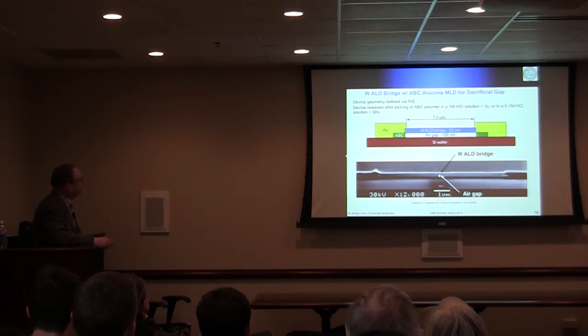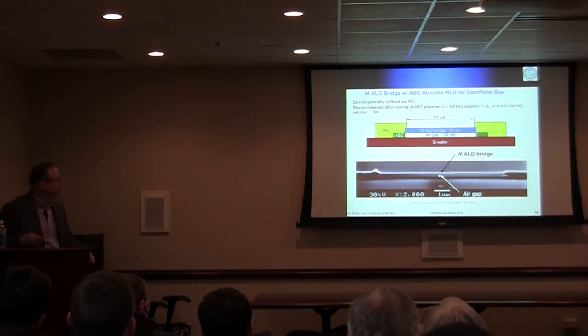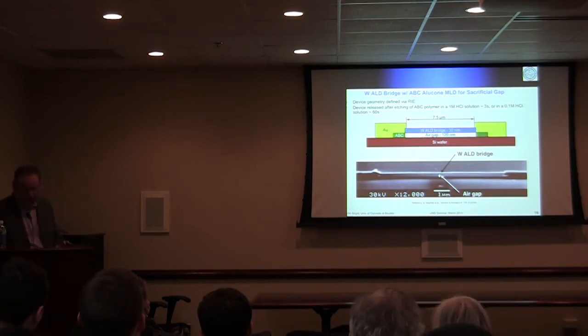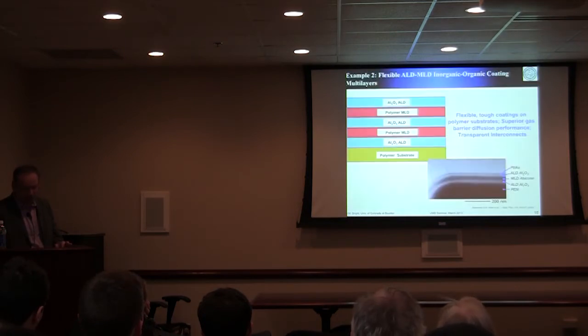And so now, once you realize that you can make this type of technology, then you can create a custom-made surface micromachining process in-house that uses ALD for structural layers, not just coatings. And because you can make removable layers that are precisely controlled in thickness, you can make very, very small gaps. So this one was done with MLD, alucone.